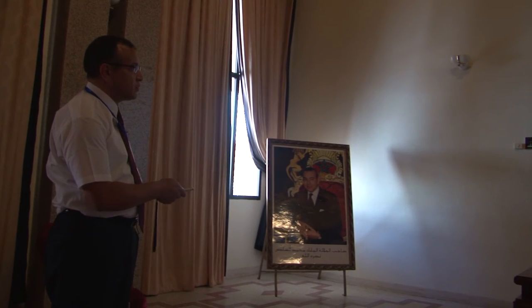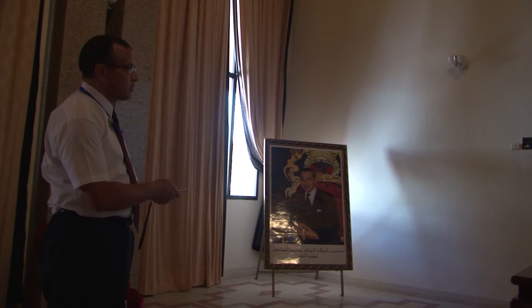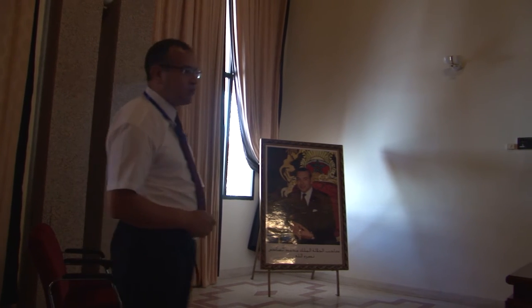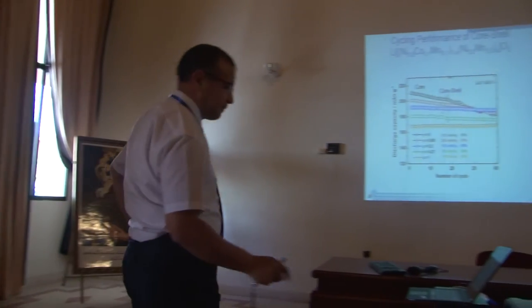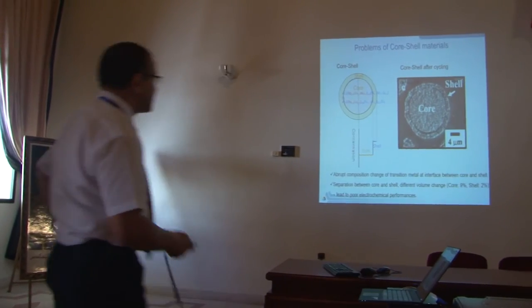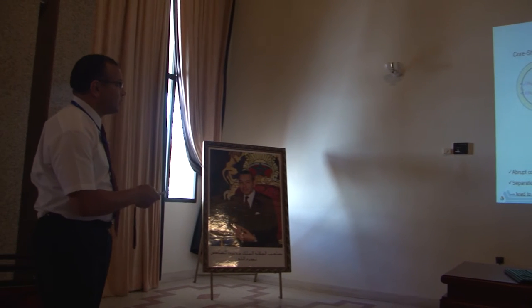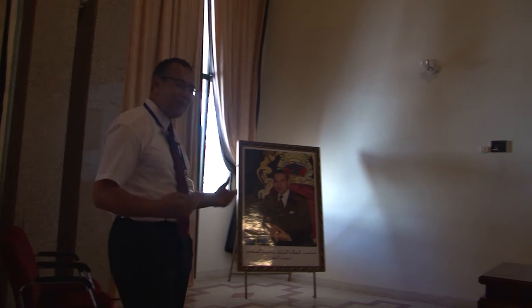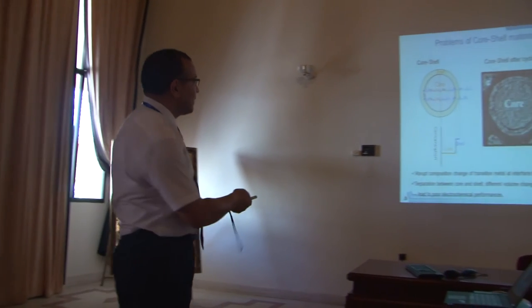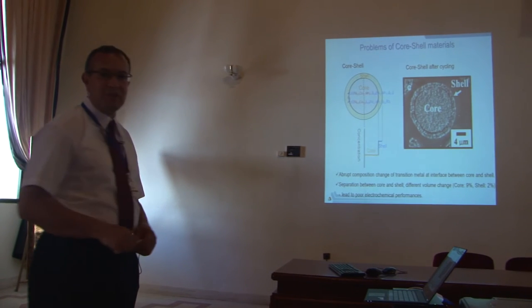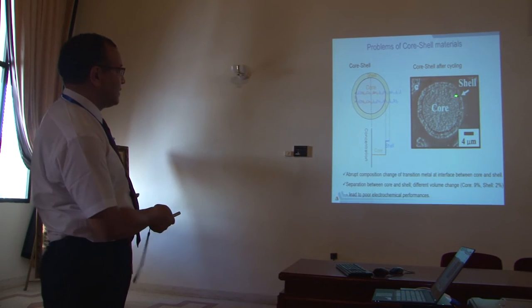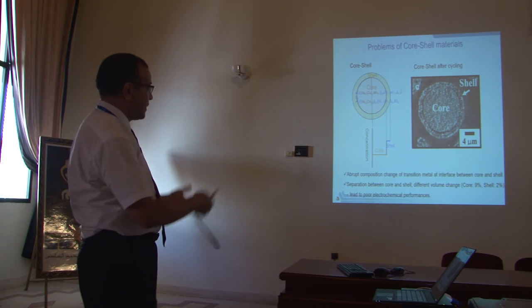Core alone, capacity drops. When you start adding manganese at the surface, depending on the concentration, you stabilize the system because you have less nickel at the surface that creates surface reactivity. The problem is that you have two materials, one on top of the other, that swell at different rates, one at 9%, one at 2%. So obviously you expect at one point you have a kind of separation between the two. And once you have that, the lithium will not be able to move through that and the capacity drops.